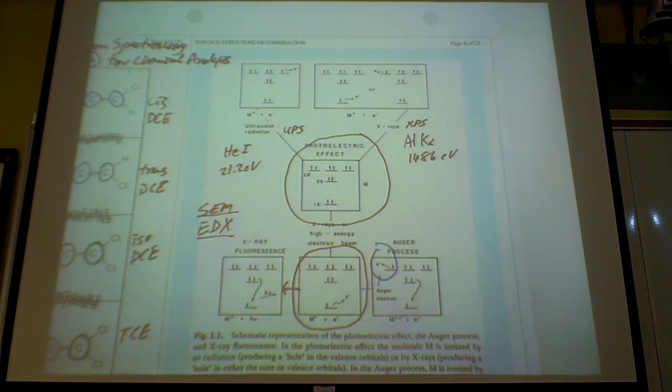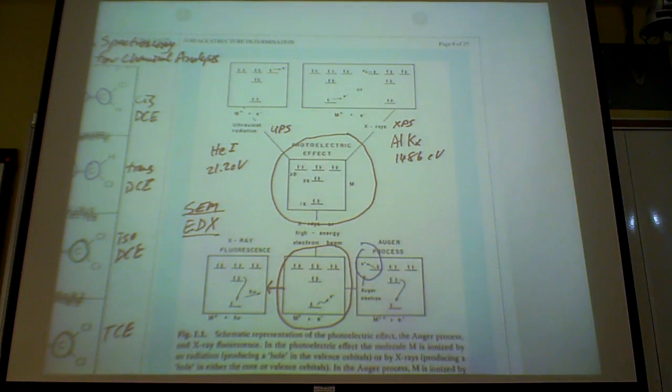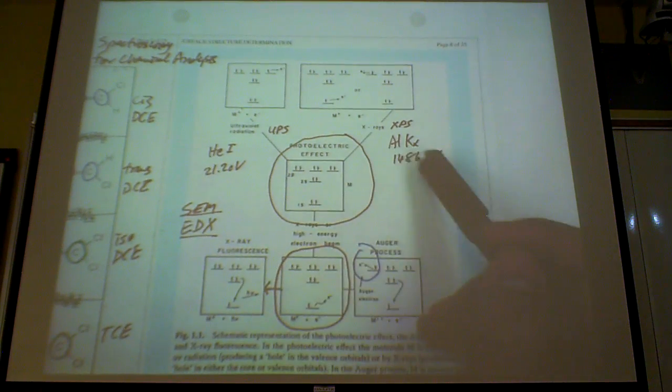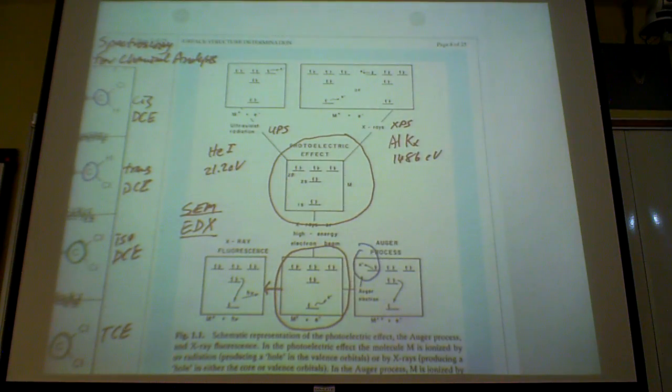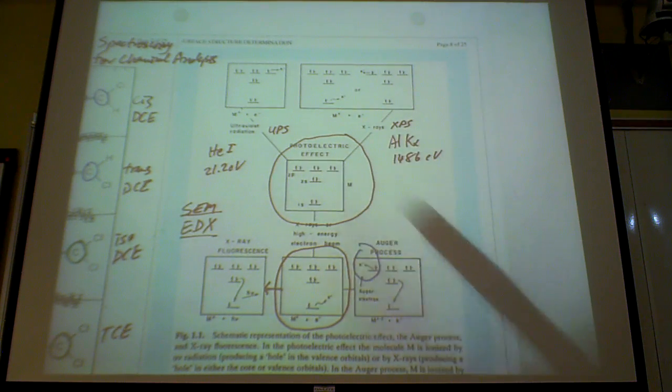Okay, so this is aluminum K alpha, meaning that you are exciting the aluminum 1s electron up to some upper state, and then this upper state comes back down to the ground state and emits a photon. And because it's the difference in two energy levels, this photon is always 1486.6 electron volt, if you like. So it's quite precise radiation that you see. It's a single line. So the aluminum K alpha line is about 1500 electron volt.